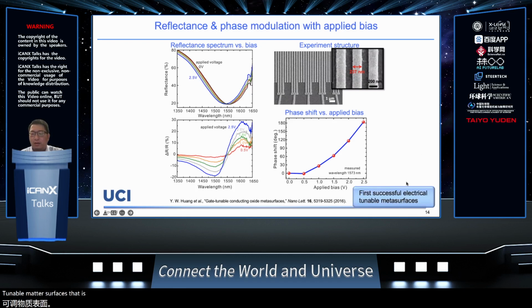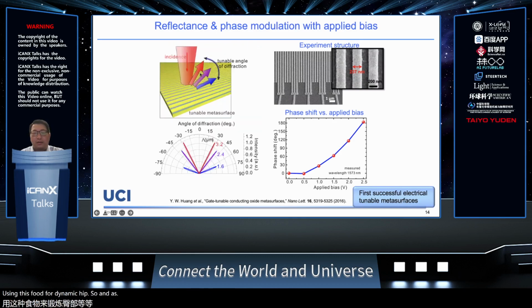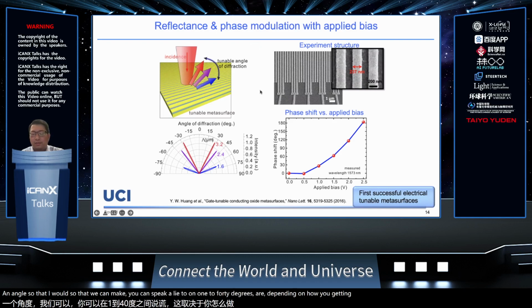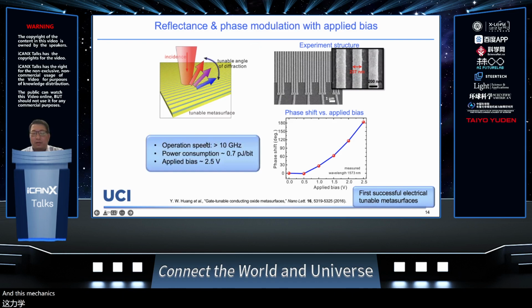So this is actually one of the earliest successful electrically tunable metasurfaces using this field effect dynamic. As I said, we can gate the structure so that we can steer the light to different angles, even to around 1 to 40 degrees, depending on how you gate the structure. And this mechanism is also quite efficient.